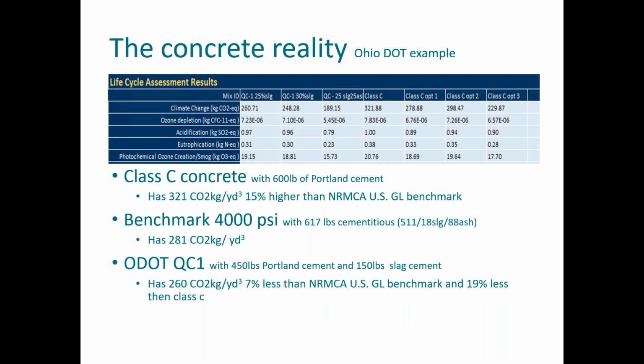Now, when we go to concrete and the concrete reality, we're going to look into this. You're going to see this kind of graph more as we go further on, because that's part of the Slag Cement Association's LCA tool. But in this case, we're going to take the DOT example, Ohio DOT. Back in 2012, they switched from prescriptive based mixes to performance based mixes. If we look at their bread and butter mix, their Class C concrete, it consisted of 600 pounds of Portland cement, and they had some variations of it. If we look at that first column where it says climate change, CO2 equivalents, we can see that now that they've gone to performance based, where they're allowing the use of slag or variations of it, the global warming potential has gone down.